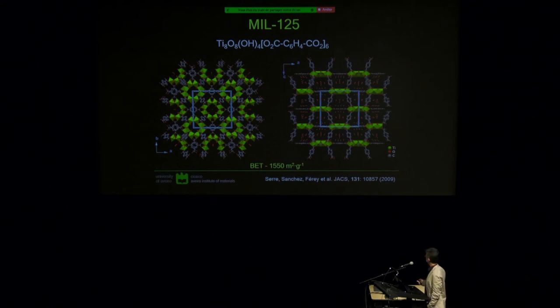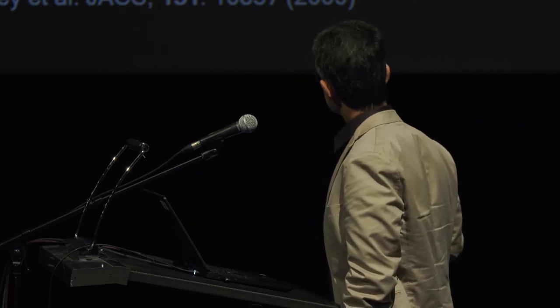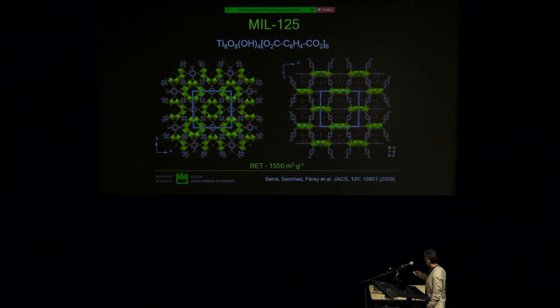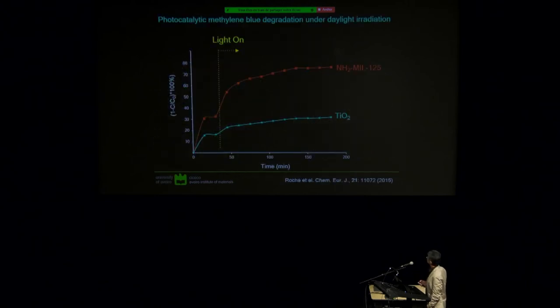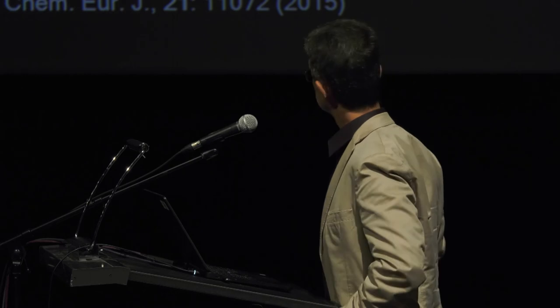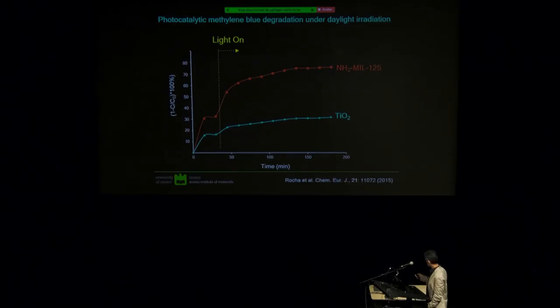So we started with a metal organic framework we just took from the literature. In fact, from a paper published by Clément Sanchez and Gérard Férey in 2009. Beautiful structure in itself. It's really fantastic structure. And this contains titanium, and it's a good photocatalyst. Just to give you an idea, if you take a probe molecule, methylene blue, and we study photocatalytic degradation of methylene blue under daylight irradiation, this is the curve here. In the absence of light, once light is turned on, degradation goes up from about 30-35% to over 75%. It works much better than a normal, commercial titanium oxide catalyst. So this is a photocatalyst.